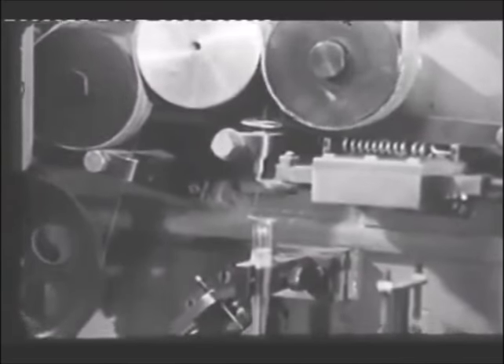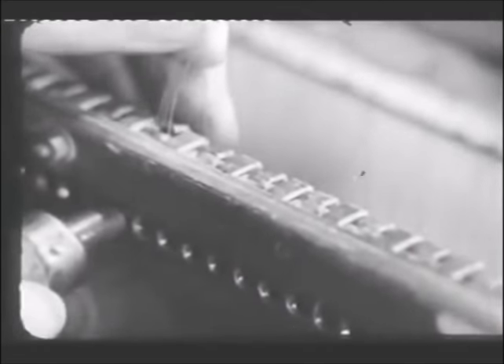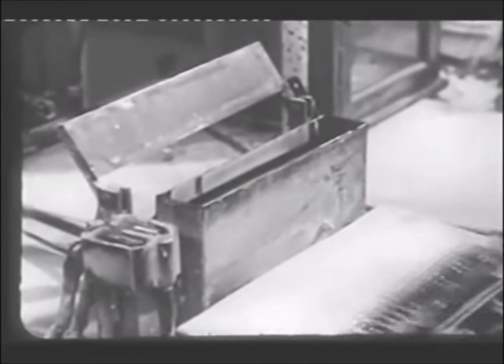Heaters for indirectly heated cathodes are made from tungsten wire. The wire is bent to an M or V shape. These wires are next clipped into frames, immersed in a bath containing insulating material, which is later baked on by passing a current through the wires.